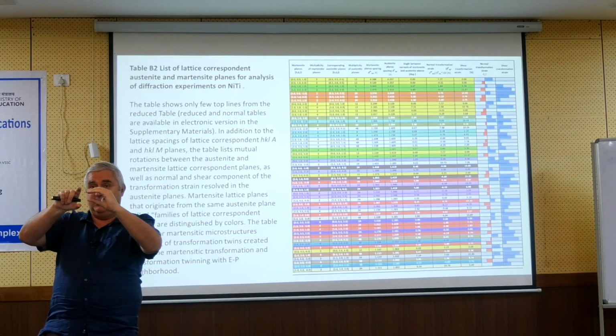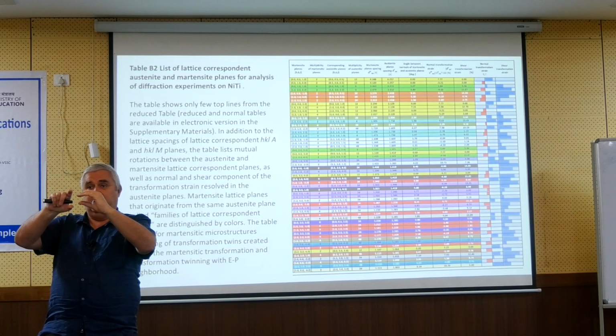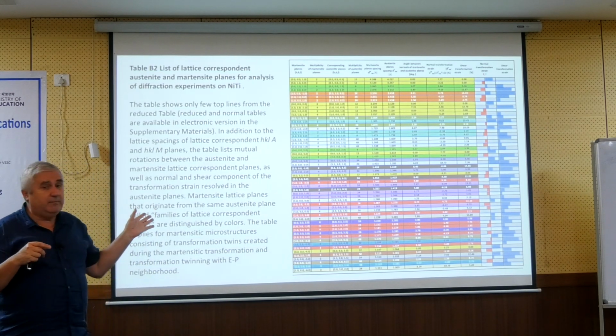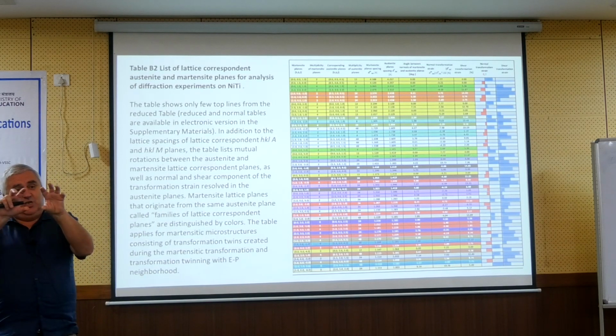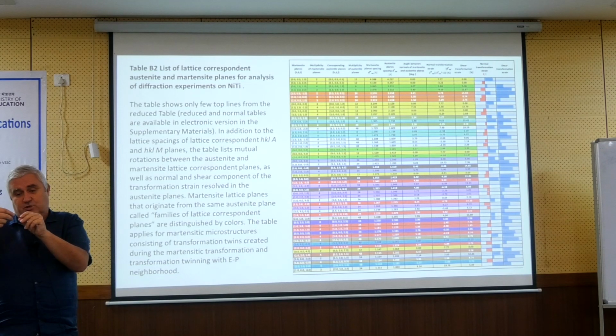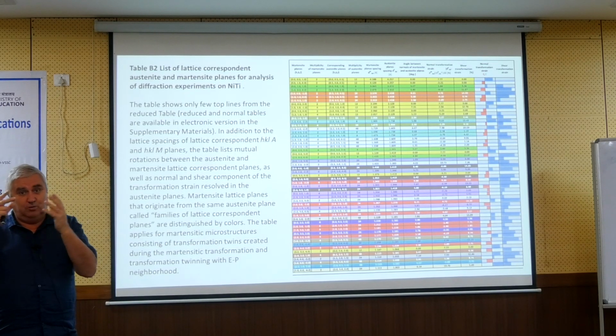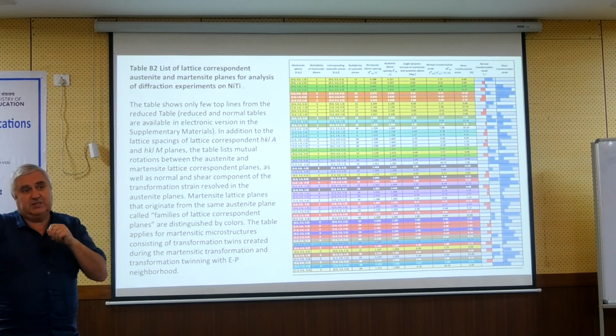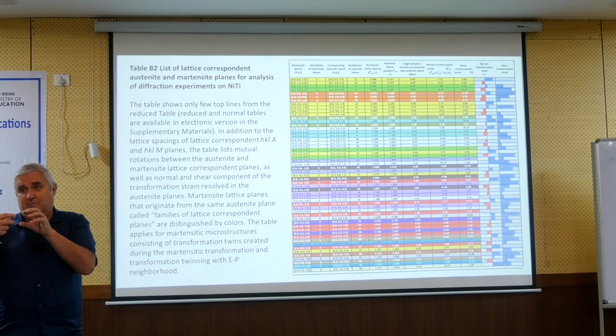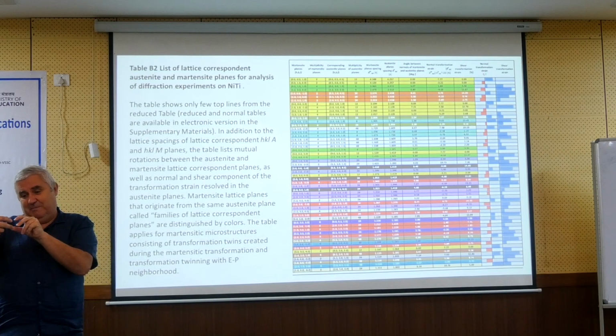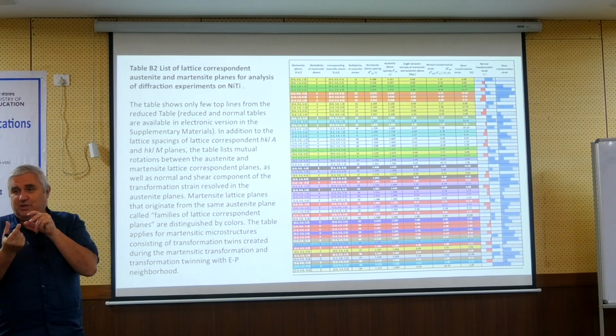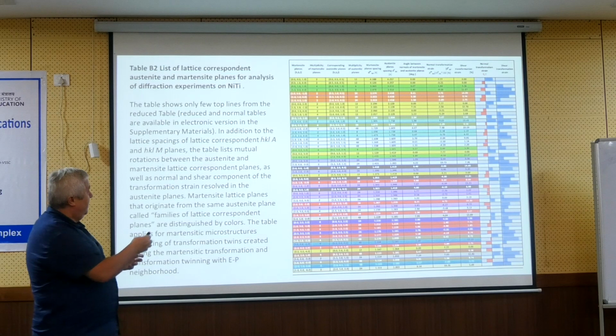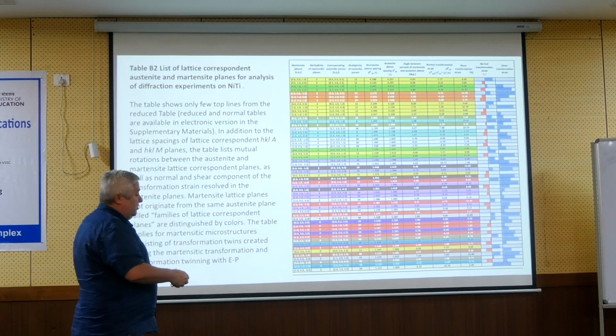If the lattice spacing is larger, I have extension like 11%. And I will show a little bit later that this change from austenite to martensite is actually expansion along one direction and shortening along two directions. Only from this you can understand that if I have a NiTinol, I can obtain more strain in tension than in compression, because the martensite becomes long in one direction and shorter in two directions. So this table is the result of this process.